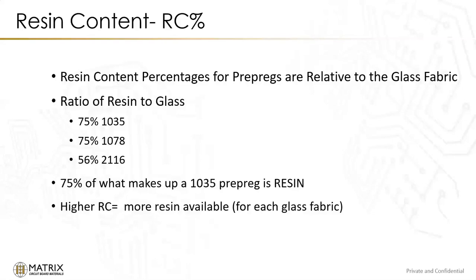The other thing to understand is the resin content percentages for prepregs are relative to the glass fabric that we're talking about. So we're looking at a ratio between glass and resin. So a 75% 1035, it's 75% of what makes up a 1035 prepreg is resin. And the same for 75% of what makes up a 1078 is the resin. The same thing for the 2116. And the higher resin contents, of course, should be related to more resin available, but that's only if you're talking about within each specific glass fabric.